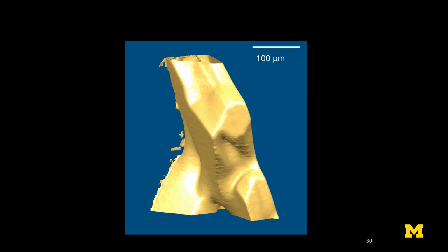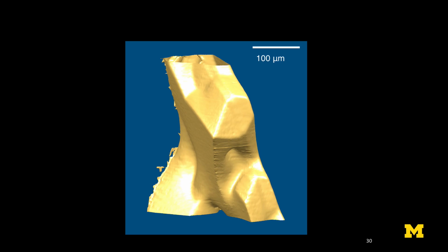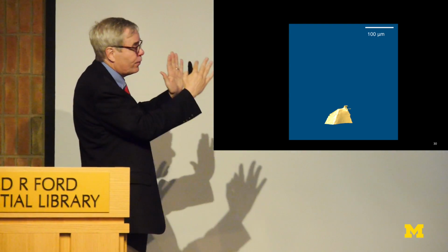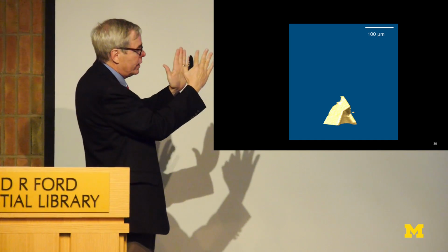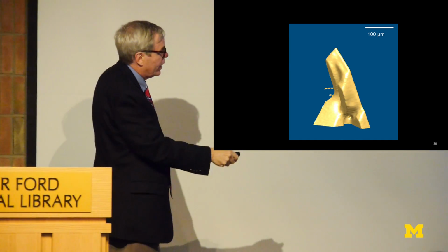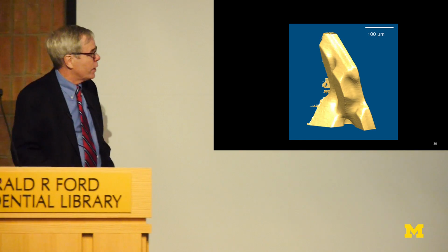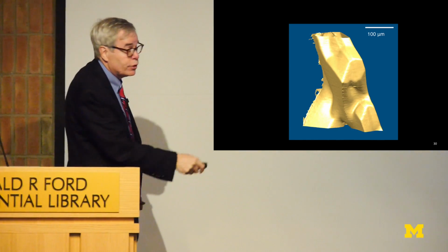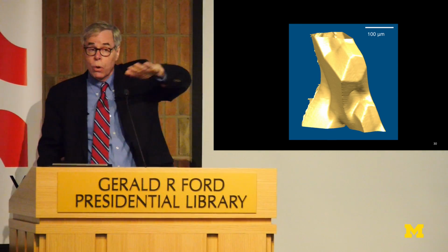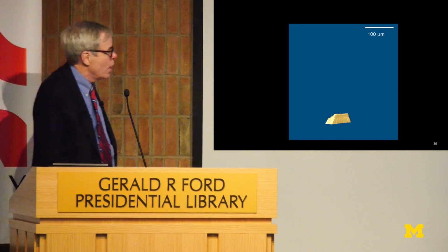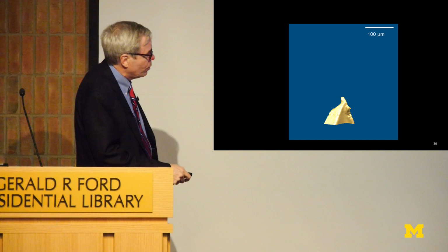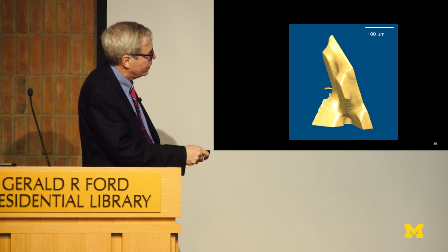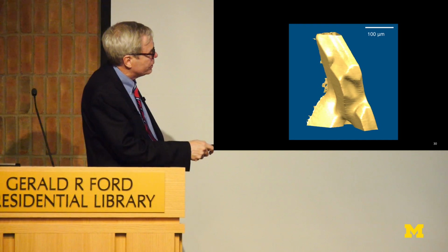So the first thing you'll note is that this doesn't look like a snowball, right? It just doesn't grow up isotropically. It grows up highly anisotropically, and it's basically bounded by 2 facets. That's this one and this one that are 111 facets for the materials people in the audience. And these things have very slow growth rates. This is just like the basal plane of snow. It does not grow very fast. But look at the edges. And the reason why this grows so fast is if you look at the edges that are bounded by these 111 planes, it grows much, much, much faster.